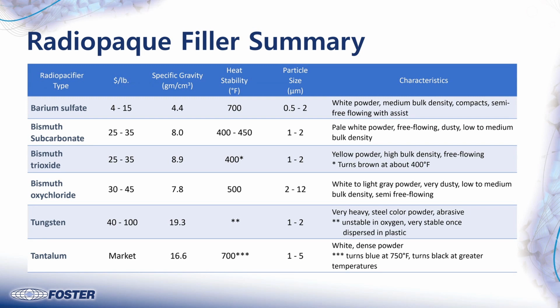Bismuth oxychloride, I kind of like bismuth oxychloride because it gives you a little bit higher temperature stability. Also, because of its shape, almost a platelet shape, it gives you a little different surface finish. So if you're looking for a glossy, smooth surface finish, you'll see bismuth oxychloride used in a lot of cosmetics, lipsticks and that sort of thing, because it's a shiny, smooth look. So you might use bismuth oxychloride in something where you want almost that shiny metallic look on the surface.